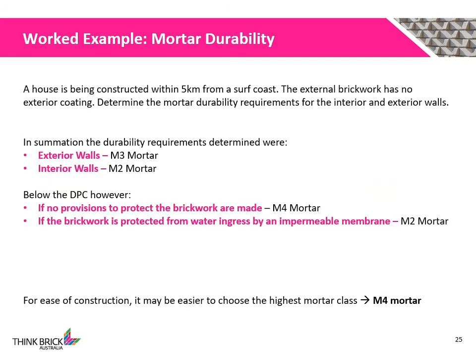In summary, external walls shall use M3 mortar and internal walls shall use M2 mortar. Below damp proof courses, M4 mortar shall be used if no provisions are made to protect the brickwork, while M2 mortar shall be used if the brickwork is protected from water ingress by an impermeable membrane. For ease of construction, it may be easier to choose the highest mortar class — in this case, M4 mortar may be chosen for the entire project.